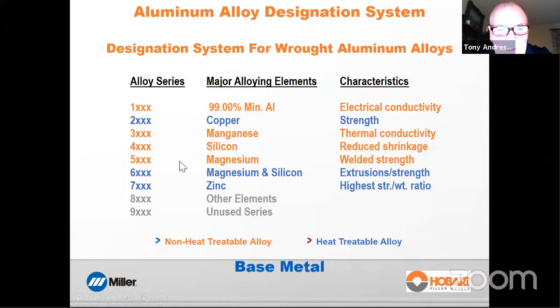5000 series, magnesium. This is the workhorse. It has good welded strength. It's a strain hardened material, but it still keeps its strength pretty good even after welding. Used in many, many applications. 6000 series, magnesium and silicon, which form magnesium silicide, remember, heat treatable. It's used as extrusions primarily because of its strength and its flexibility. It can extrude really, really well. Why do we not see 5000 series extrusions? Because it's strain hardened so fast, it's really, really difficult to extrude 5000 series. It can be done, but it's very, very slow and it's very, very expensive. So you don't see them often. They're custom made usually. 6000, I'll guarantee you, you go in any store and you buy an aluminum extrusion, it's going to be a 6000 series.